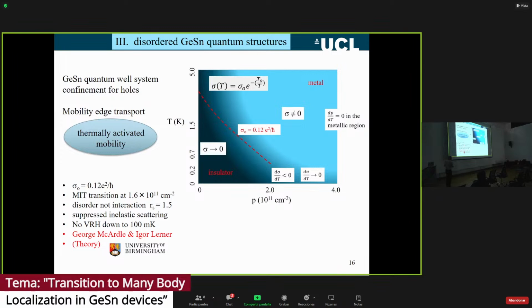If we look at the interaction parameter, the question is: is it interaction or is it disorder? Is it disorder in the lattice or is it carriers that are interacting? The interaction parameter is really quite small, just 1.5, so it's really disorder. We haven't really got interaction in the system. What we've also done is manage to suppress this inelastic scattering, this non-hopping behavior. There's no variable range hopping down to 100 millikelvin.